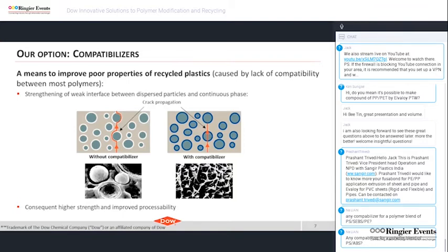Our proposed solution to improve poor properties of recycled plastic caused by lack of compatibility between most polymers is to add compatibilizer to strengthen the weak interface between dispersed particle and continuous phase. The left-hand side figure shows the dispersion of two incompatible polymers without compatibilizer, and there is a clear interface between the dispersed particle and the continuous phase. Hence, the crack propagation would be expected to follow preferably at the weak interface between the two polymers.